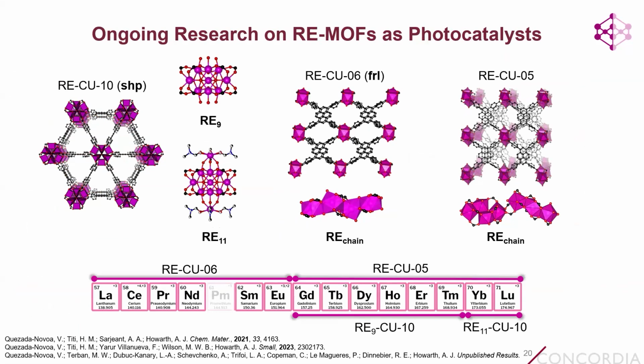Whereas if you look at rare earth CU-05, we have a mixture. Some of the lanthanides have a coordination number of 9, but most of them have a coordination number of 8. And so I think because it's difficult to force the early lanthanoids to have a coordination number of 8, we can't make these specific motifs that are unique in this structure, or at least it's more difficult. And we have the same problem with our cluster-based MOFs. So far, we've only really been able to make them with the late lanthanoids. All the rare earths in those have a coordination number of 8, sometimes with very low occupancy of a terminal water in a 9th position. But we're having a lot of difficulty trying to make the early lanthanoids, probably because it's difficult to force them into that specific coordination number and geometry.